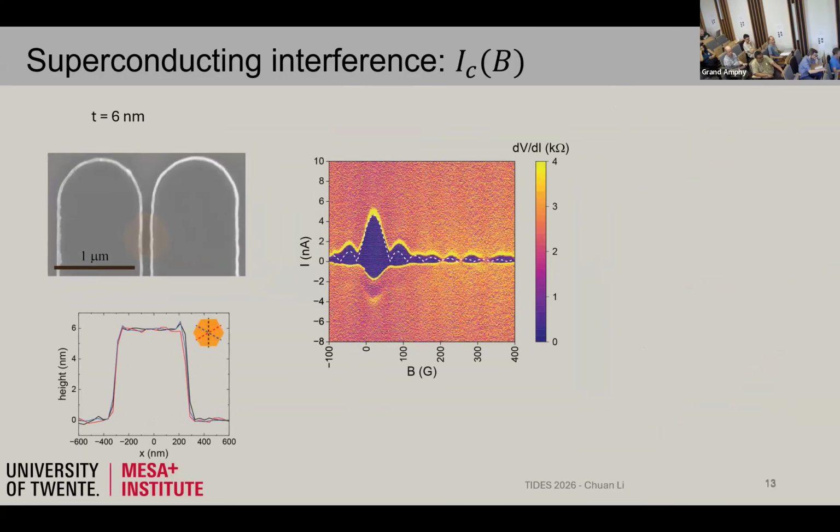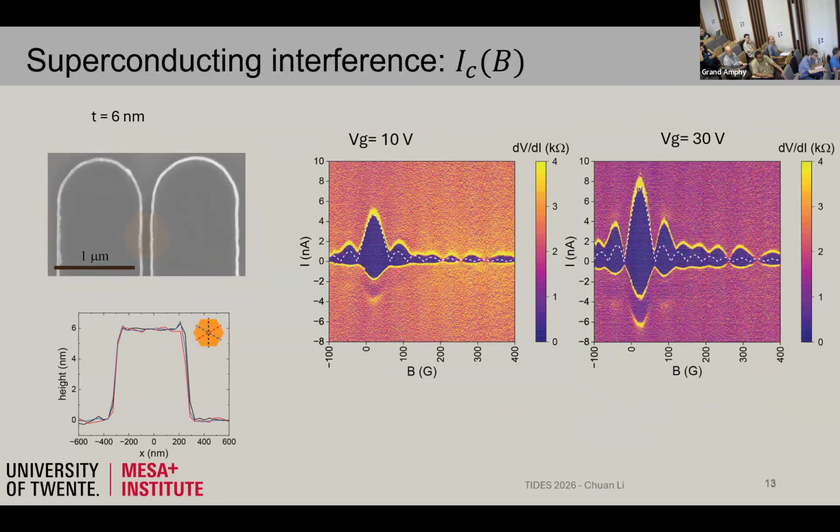So at the end, we managed to measure supercurrents in such tiny flakes, and in this case, it's 6 nanometer thick. So it's actually a little bit higher than the theory part. But remember that we have done this in ambient environment, not encapsulated. So our argument is that naturally they will be oxidized at the surfaces, so the effective thickness will always be lower, at least 1 nanometer lower.